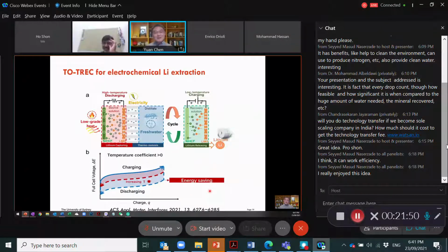Thank you. So that's where we propose this idea. We couple thermal osmosis, which you can use to generate fresh water as well as concentrate the source solution, with the regenerative cycle here. Then they will be able to do the lithium extraction at a relatively higher temperature, 60 degrees, at the same time that you do the charging at 20 degrees.